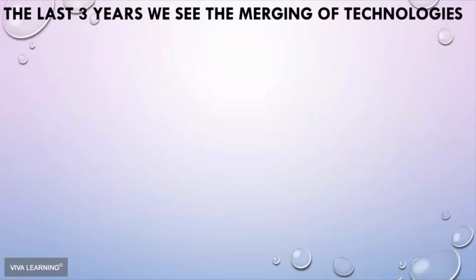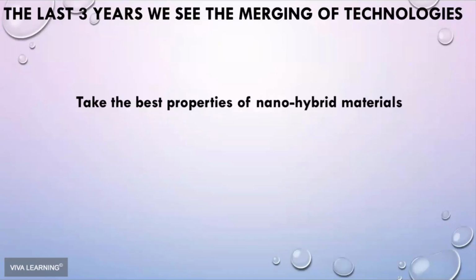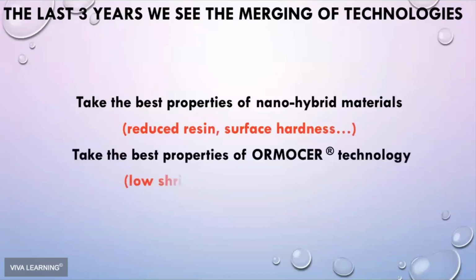And in the last couple years, Voco, 3M, Dentsply have all been trying to reinvent these chemistries or redevelop the emergence of these technologies, and taking the properties of a nanohybrid material. And we kind of mentioned this earlier, the reduction of the resin and the surface hardness of the material. And if you could combine it with ORMOCER technology, with low shrinkage, and this is where doctors start to say, wow, how much shrinkage is involved with some of this new technology? We're getting close to 1%, where in the past we would see 3 and 4% shrinkage with much of the materials that we're using.